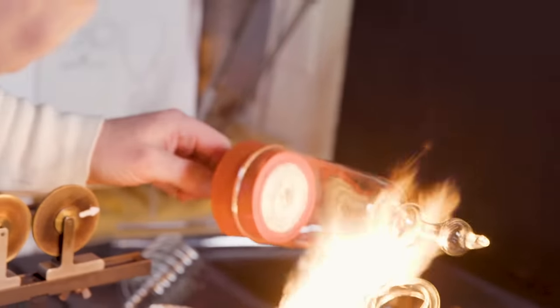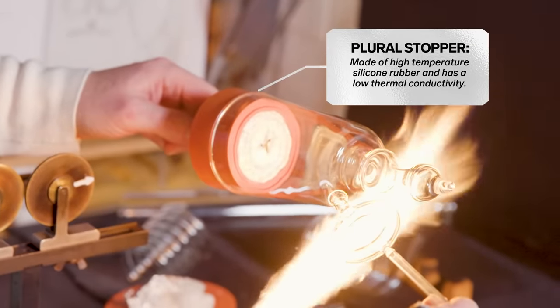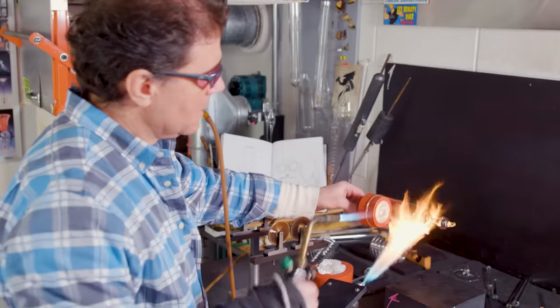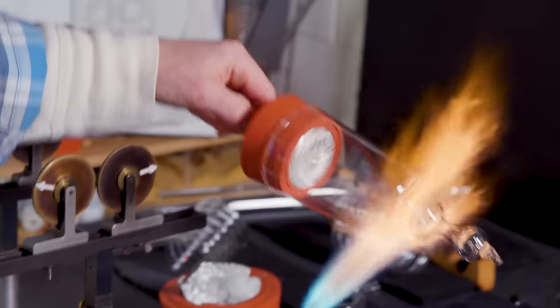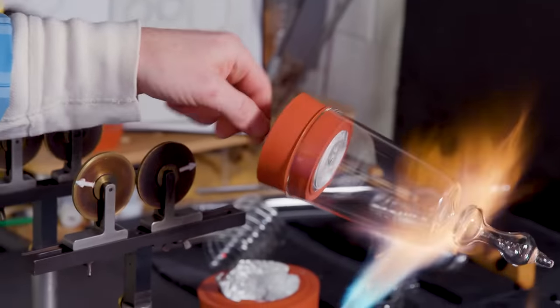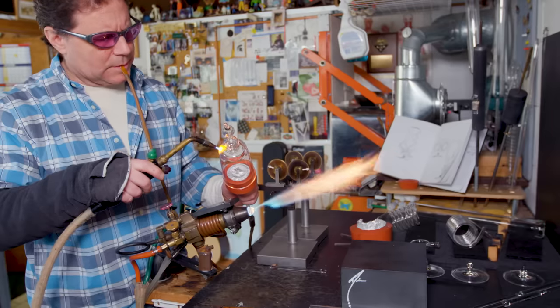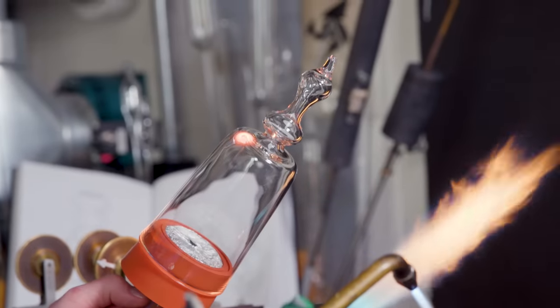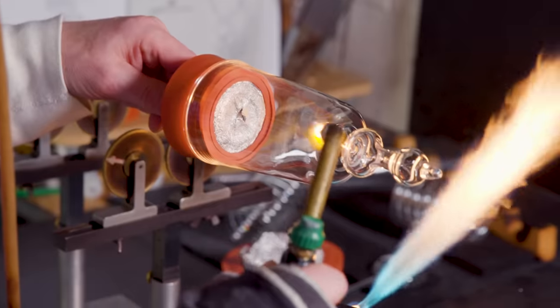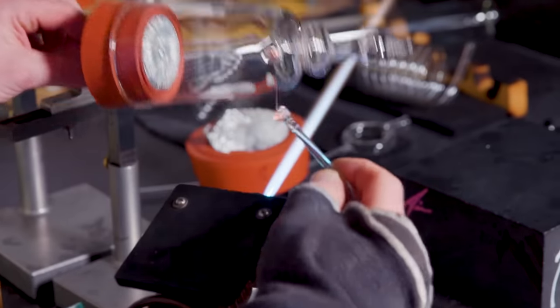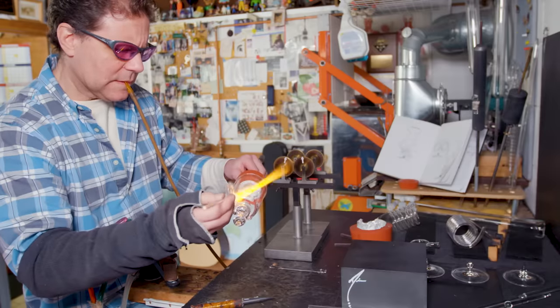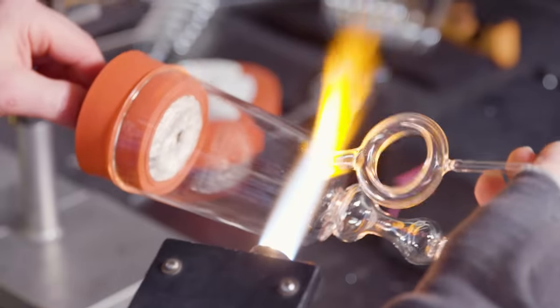The plural stopper is just a big stopper and I use it as a holder with a handle so I can put my cups on it and hold them in the flame and still be able to blow. I use a small hand torch to heat just a very small piece of the glass. I blow a blister. It looks like a blister. And then I pop that open and then I'm ready to seal on any kind of side arm or connection.